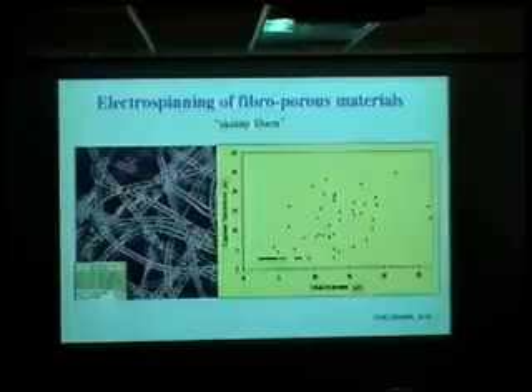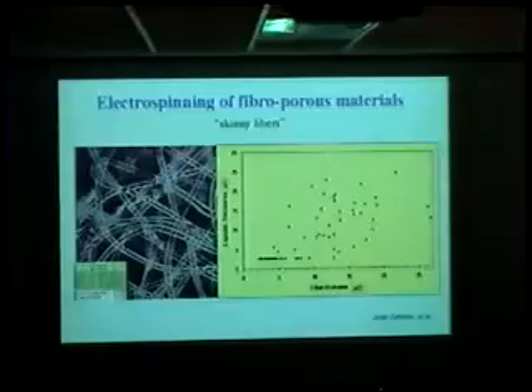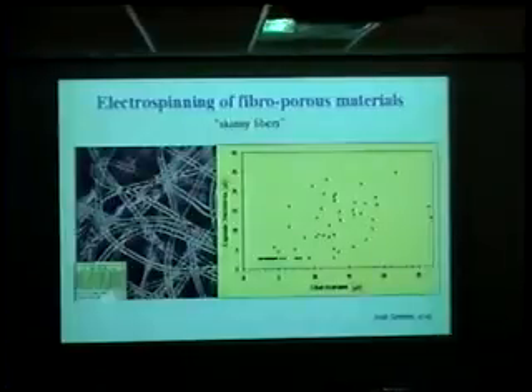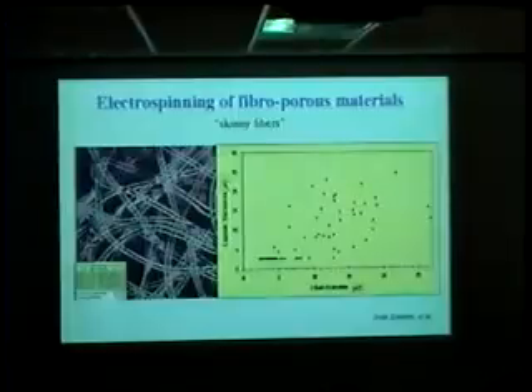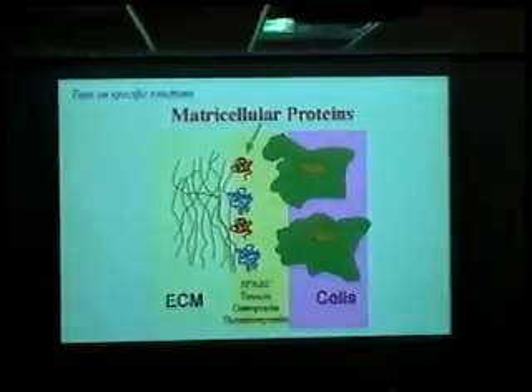Is there a question? Are those Teflon fibers? These are polypropylene in this case. I think Joan would think that it's independent of the material. It's a size effect, which is what's seen with the pore size effect too. So geometry and pore size does seem to have some very profound effects on healing.